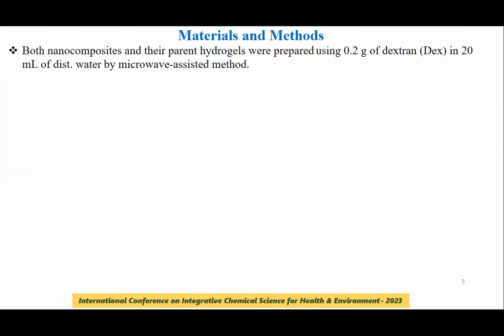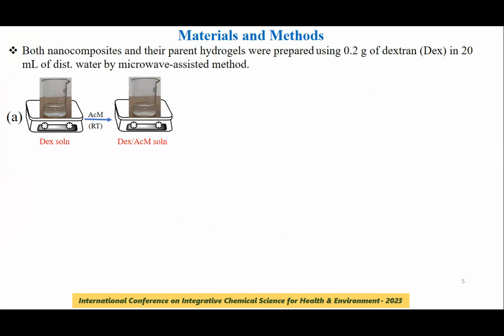Material and methods. In the preparation, both the nanocomposite and the parent hydrogel were prepared using 0.2 grams of dextran in 20 ml distilled water by a microwave-assisted method as a green approach. In brief, the monomer ACM was added to the dextran solution at room temperature. Then, after thorough stirring, MBA and APS were added to the resultant solution, followed by microwave irradiation for about 15 to 20 seconds to get the hydrogel.